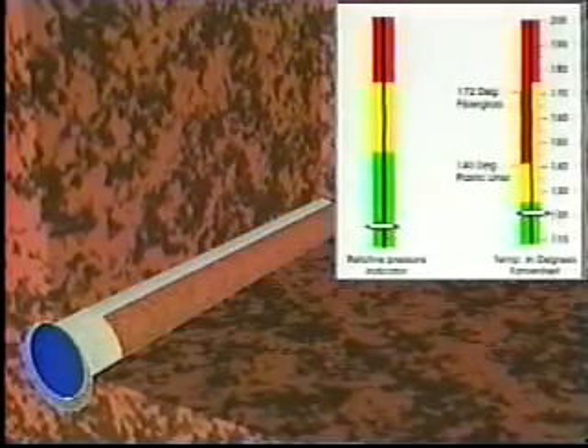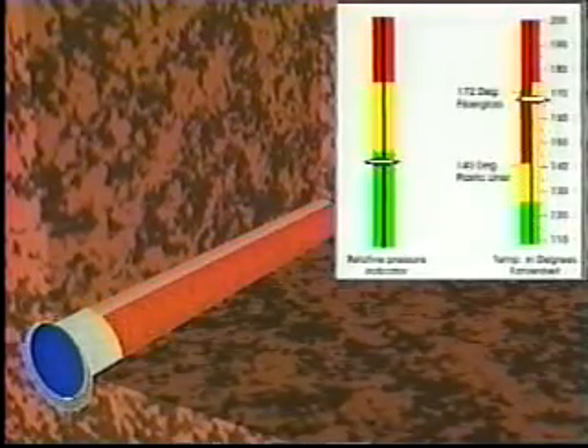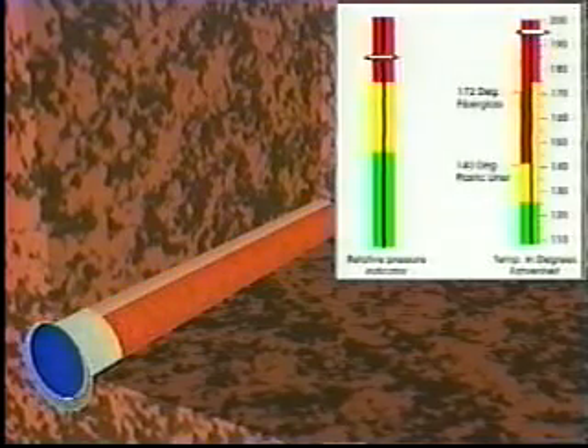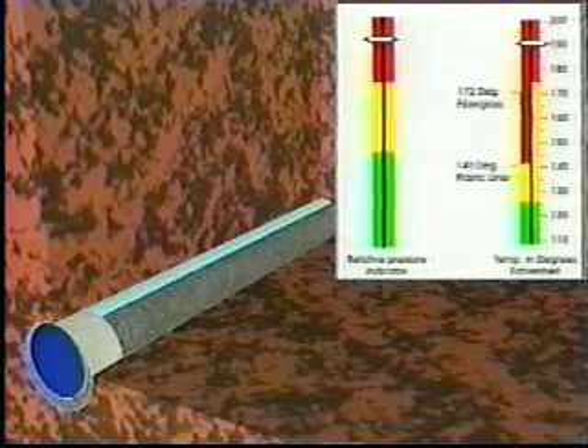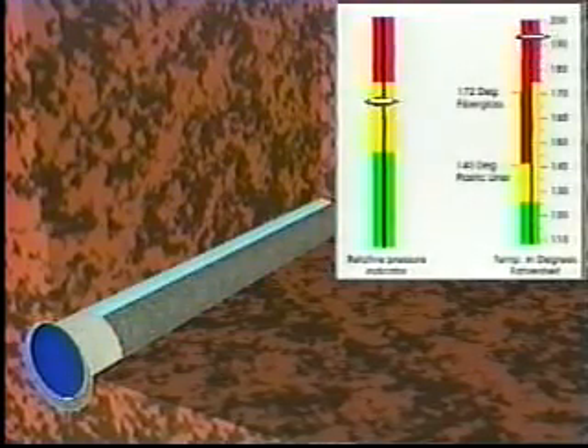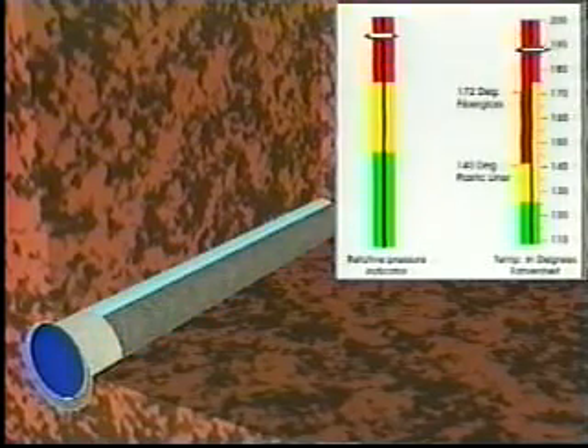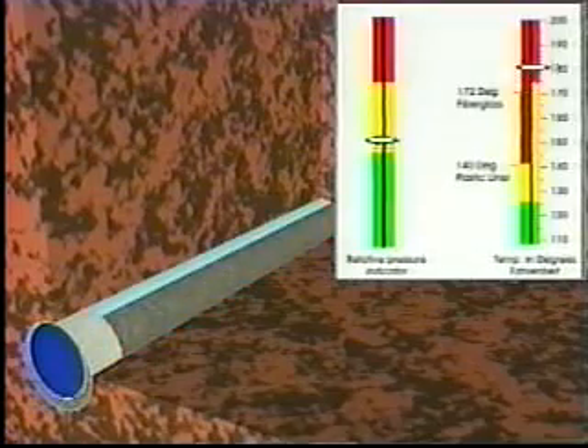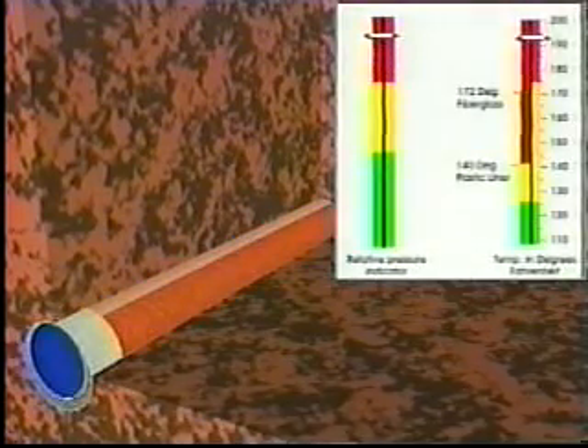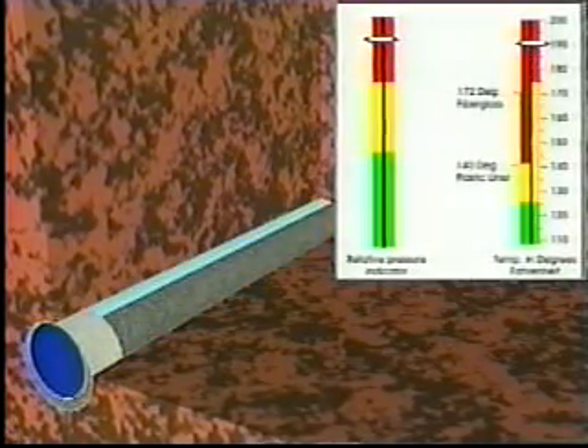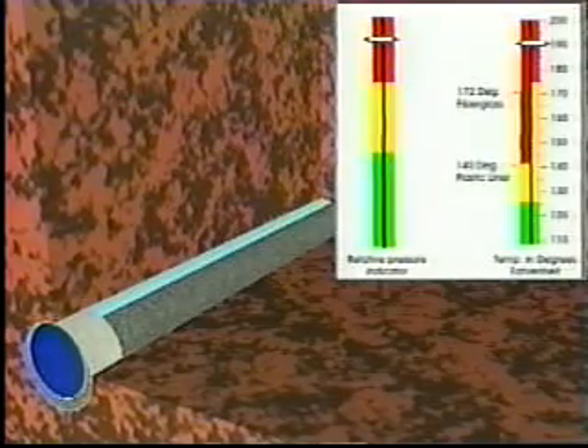But that's not the only problem. There's the natural heat generated by hydration during the curing stage of the concrete. During the hydration of ordinary cement slurry, temperatures typically range between 180 and 200 degrees Fahrenheit, substantially more than the heat distortion temperatures of 140 degrees for plastic liner pipe and 172 degrees for fiberglass.